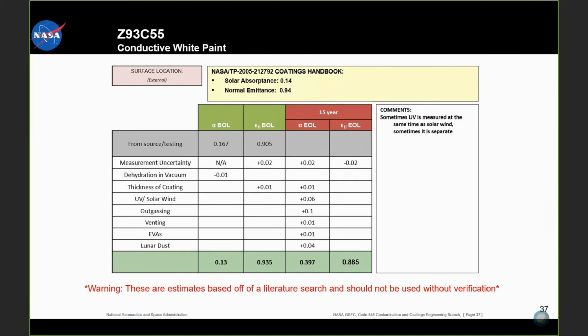So here we did an example for Z93C55. This is a conductive white paint that's of interest for Gateway. So you'll see that we started with the beginning of life absorptivity and the emissivity, and then we went through and just added up. So for example, what was the measurement uncertainty, the thickness of the coating and uncertainty related to that. And then we went through for the UV, the solar wind, outgassing, venting, EVAs, and lunar dust. So we added up all the deltas, and then you can arrive at the end of life properties.